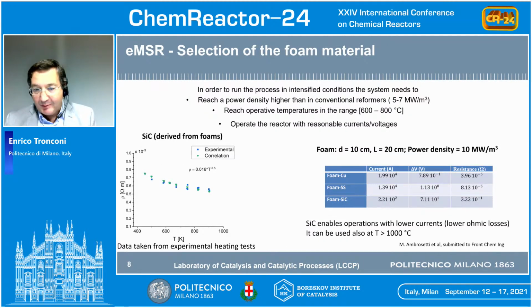So we have been exploring this concept experimentally, and open cell foams actually are commercially available in a variety of ceramic and metallic materials. So a first question here is to select the foam fabrication material. We focused first on the electrical properties requirements, and our preliminary analysis revealed that the material of choice should actually have an electrical resistivity in a very narrow range to enable reasonable currents and voltages for Joule heating. Now, for example, metals have electrical resistances which are far too low in our view. They would require exceedingly high currents.